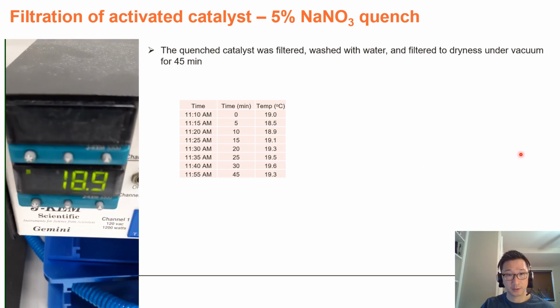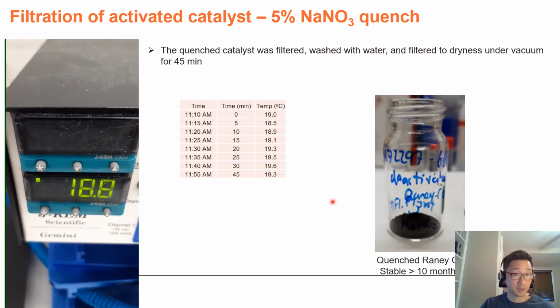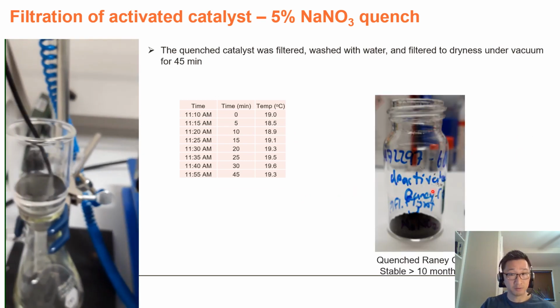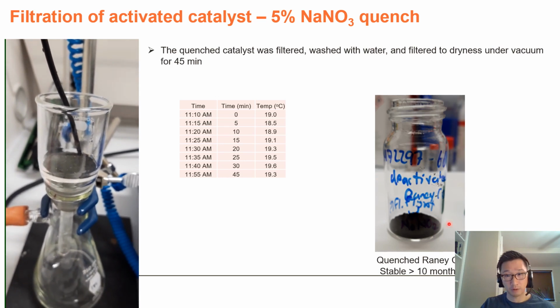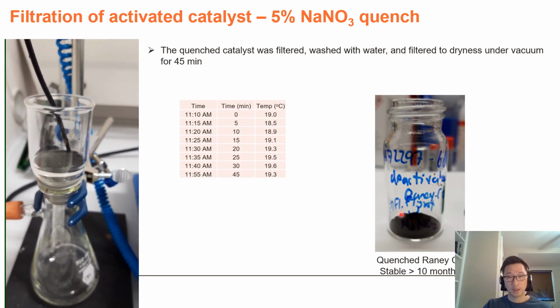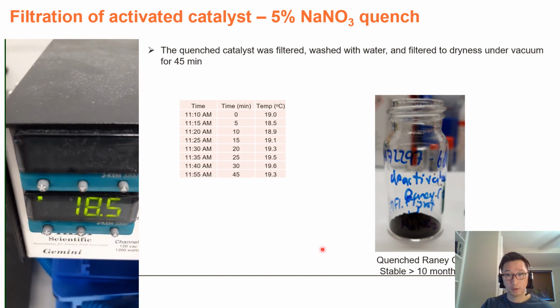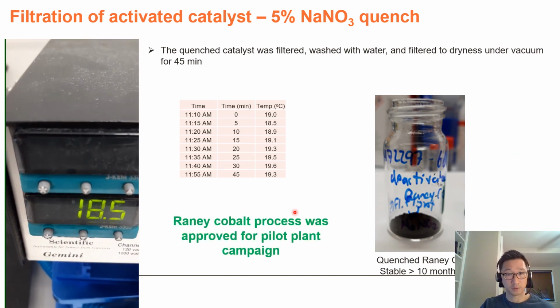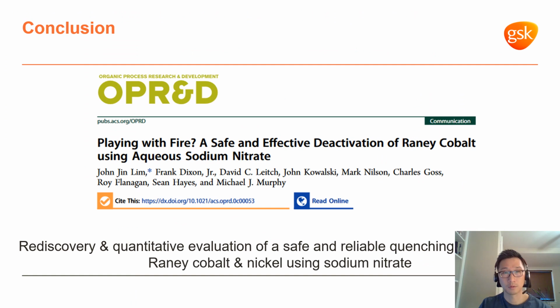The catalyst has been completely deactivated, stable to open air even when dry. And so this material is sitting in my fume hood as we speak, completely happy. No self-igniting behavior is ever observed. And thus, upon seeing the data, the Raney cobalt process was approved for our pilot plant campaign. So if you care to read about this further, we published an OPRD not too long ago.